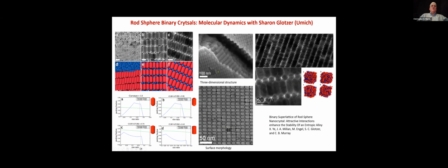So using shape of the particles and their complementary geometry and faceting really as a surrogate for bonding, for the valence that we would think of in nature's atomic building set. And in this particular example, it's a combination of rods and spheres that are co-assembled to give a binary lattice, locking in place in the small void that is created by the faceting between the rods, a position for each of those spheres. You can see a missing one down here that sort of shows you that there's still some level of defect structure in these systems.